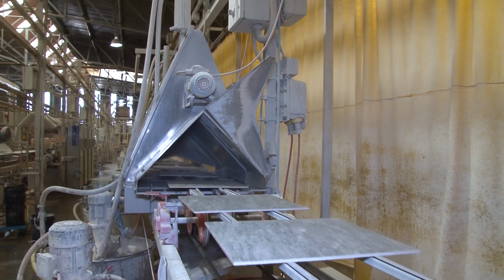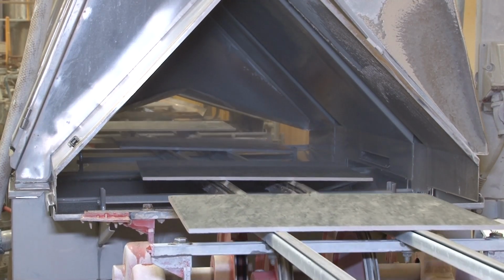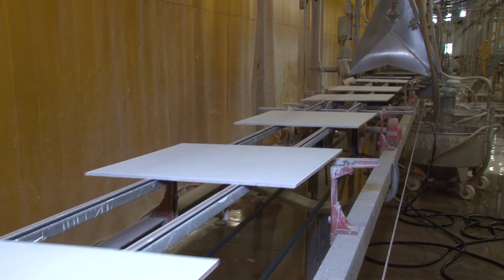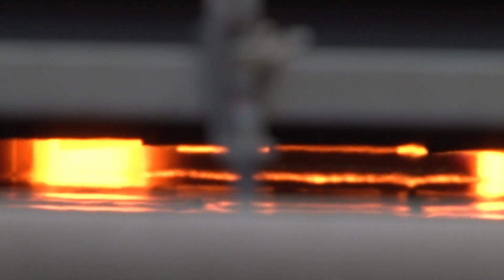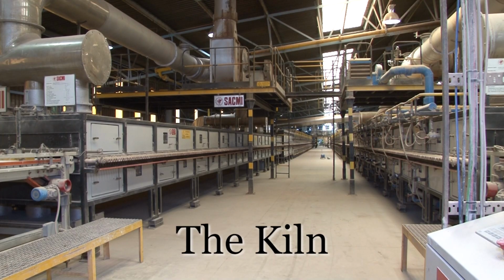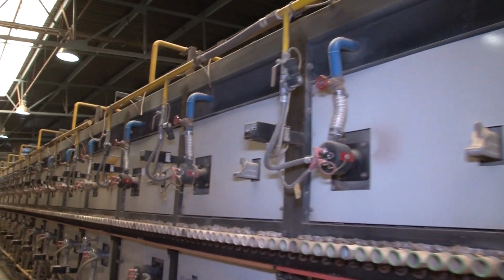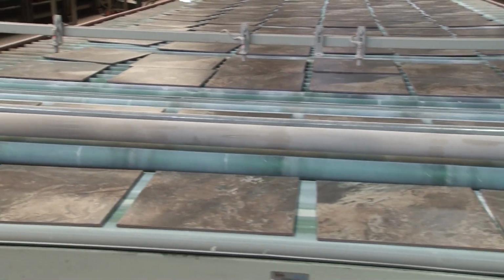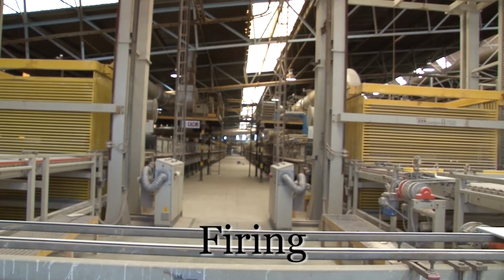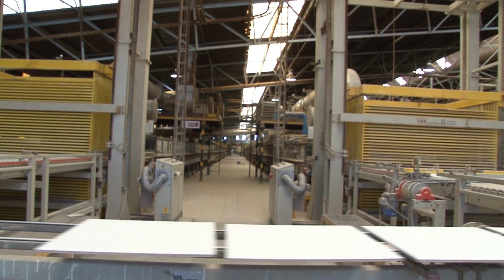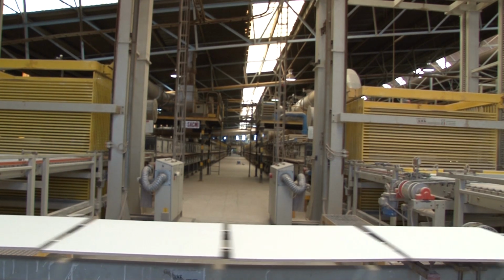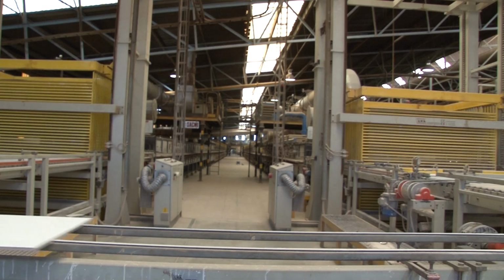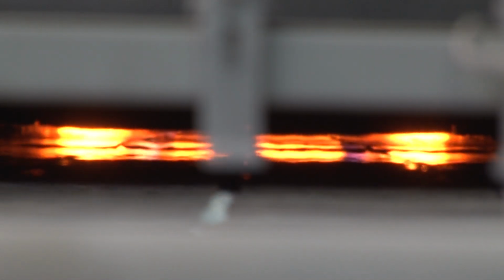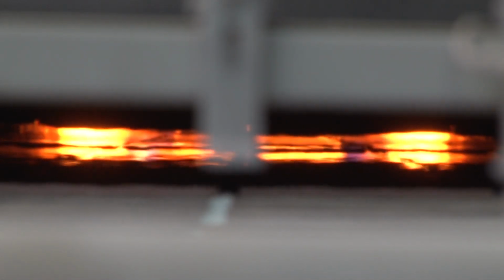A protective top coating of glaze is sprayed onto each tile. This turns white shortly after it comes out of the spray tunnel, but will become transparent as the tile passes through the firing process in the kiln. The kiln is a long tunnel heated by gas heaters through which each tile passes in a process known as firing. In the first section of the kiln, the tile is dried at low temperature to remove water from the clay. If the tiles were subjected to very high temperatures in this first phase, the water in the tiles would turn to steam and many of the tiles would explode.